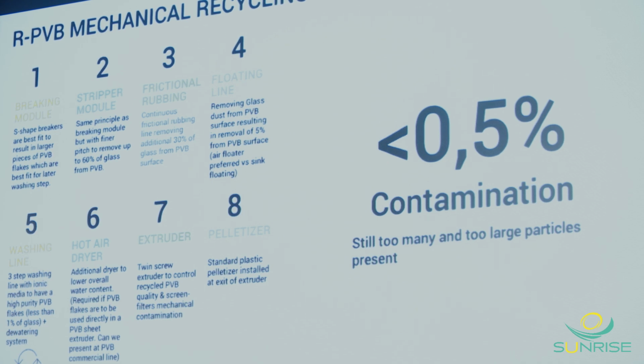If I compare this to what a typical PVB maker needs and requires, besides the percentage, which is still too high, size is also an issue. Anything which is above 50, 75 micron typically results in extrusion issues, quality issues, non-usable products. And even in the next steps, any contaminant in multi-layer applications can result in edge bubbles, all that stuff, which are typical defects that you see in laminated glazing.